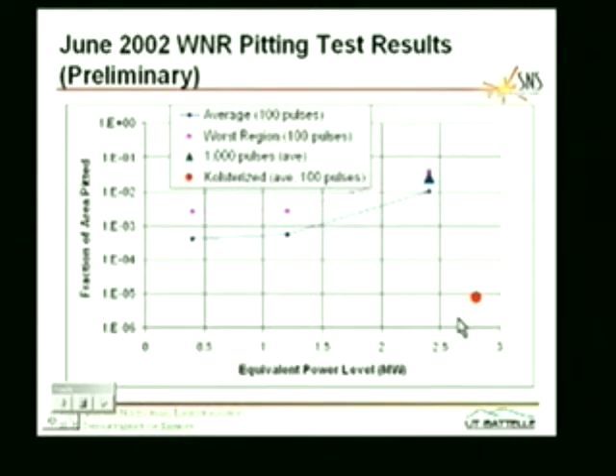This shows just an example, a measurement of the fraction of the area pitted as a function of the power level or effective power level. The crucial thing is the pressure pulse. What's the magnitude of the pressure pulse? And for 400 kilowatts, 1.2 megawatts, and 2.4 megawatts. And what you can see is there's not much difference in the amount of pitting between 400 kilowatts and 1.2 megawatts, but it goes up by almost an order of magnitude when you go up to 2.4, and it's even worse at higher pressure levels. This is good news because we're down in this range, especially when we first switch on.